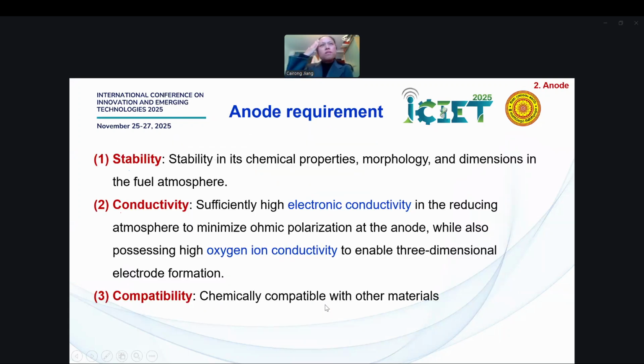For you to understand how the anode works, the first requirement is stability. It must be stable in all sorts of conditions, and here mainly in fuel atmosphere, meaning hydrogen is fed in, a reducing atmosphere, and it must be stable in that condition. The second requirement is conductivity. It must be sufficiently high for electronic conductivity and oxygen ion conductivity. For these two conductivity requirements, we need nickel to provide electronic conductivity, and YSZ zirconia is the oxygen ion conductivity provider.